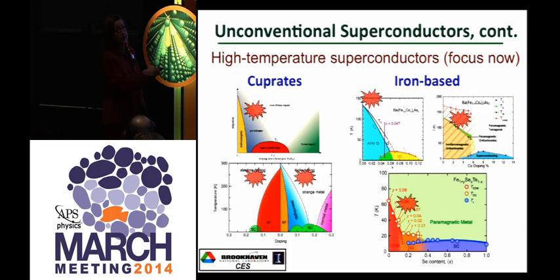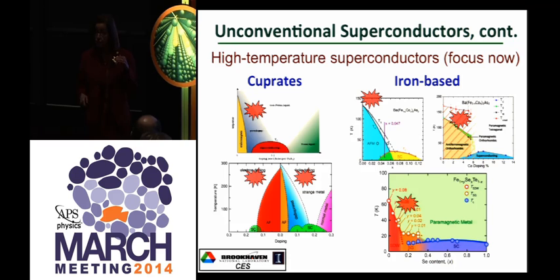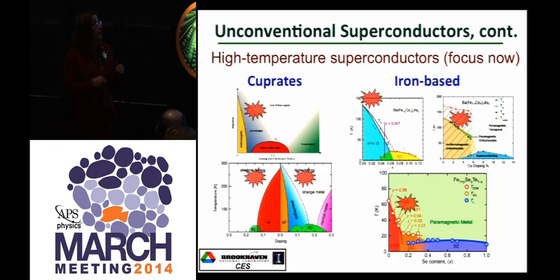This first one here is always a structural phase transition. Up here, the material is tetragonal. Down here, it's orthorhombic. Very close to that, a couple of degrees, even at the higher doping, is the magnetic phase transition. That's where it goes from probably weakly diamagnetic, paramagnetic, to antiferromagnetic, and very interesting spin structures. But up here, we find a certain kind of ordering of the electronic fluid.